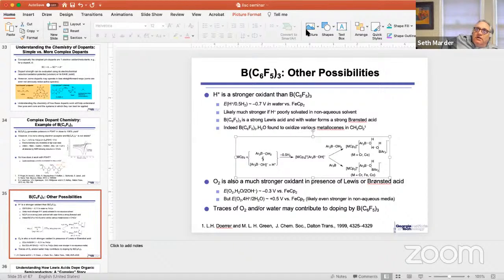So a concern that you can have, but didn't seem to be the case in the OLED that we made, is that the dopant leads, the polaron of the dopant leads to quenching of the luminescence. So in the case of the energy transfer, the thing that you need to realize is that we basically have a monolayer of dopant, okay?